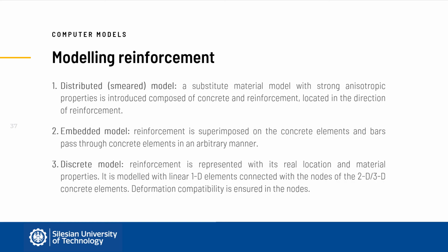Finally, the most commonly used model for reinforcement is a discrete model. In this model, reinforcement is represented with its real location and real material properties. It is modeled with linear one-dimensional elements, so bars, which are connected with the nodes of a two-dimensional or three-dimensional concrete element. The deformation compatibility is ensured in the nodes between steel and concrete, and an appropriate bond law must be defined to tell what is happening at the interface between reinforcement and concrete.